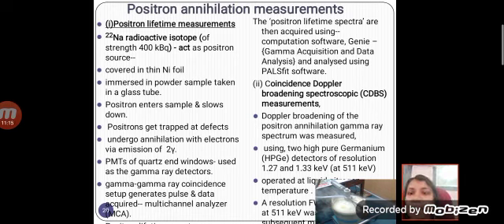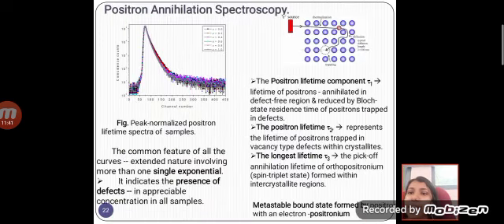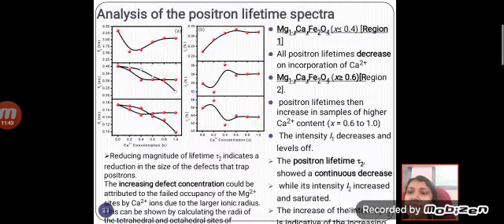So this is the experimental setup, like I have already discussed. The positron lifetime spectra is acquired using the software GENIE, gamma acquisition and data analysis. We use coincidence Doppler broadening spectroscopy measurements for analyzing the electron momentum, and the samples are cooled to liquid nitrogen temperature. We can see a typical positron lifetime spectra in this figure, for our magnesium calcium ferrite samples.